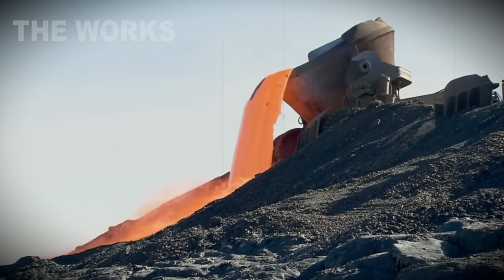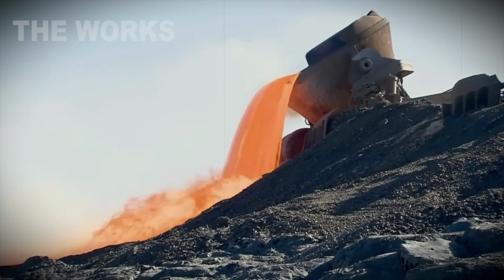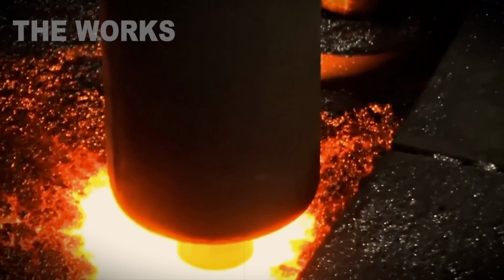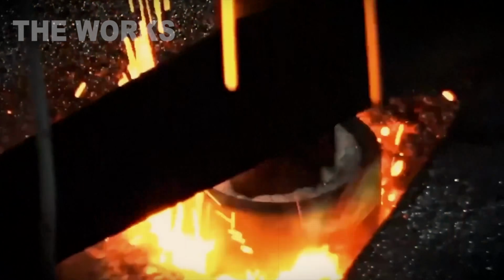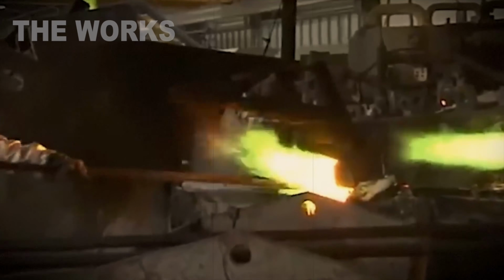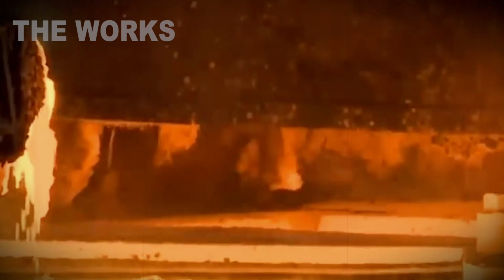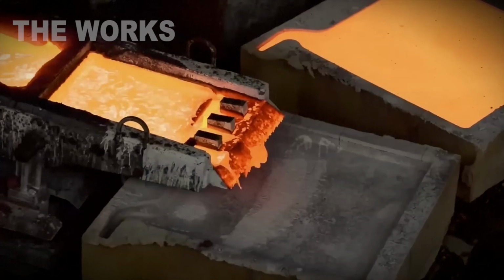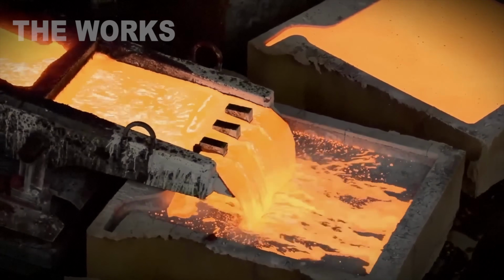Suspended concentrate particles ignite in the oxygen stream instantly, in fractions of a second. Temperature in the reaction shaft hits 2,550 degrees Fahrenheit. Copper sulfides oxidize, releasing massive amounts of heat. The reaction's nearly self-sustaining, requiring very little additional fuel.